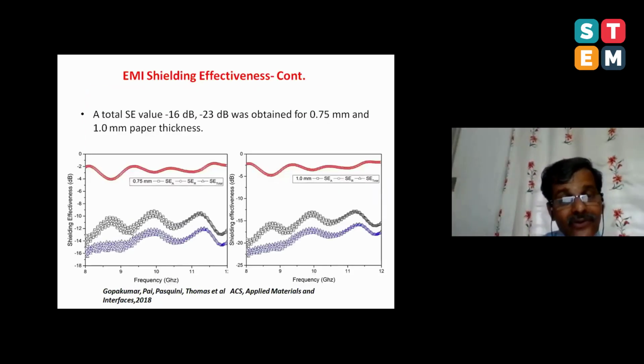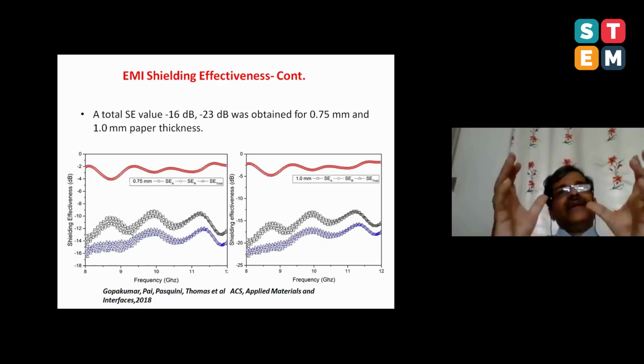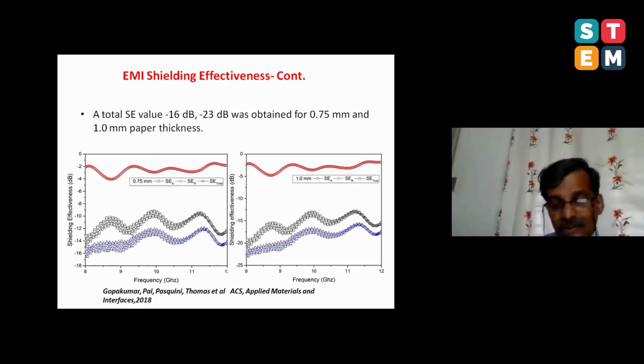What we have done, we have utilized this material for EMI shielding application, electromagnetic interference shielding application. There are a lot of requirements for EMI shielding. And look at what sort of shielding we got. We got something like 24 or 25 dB at a thickness of 1 mm. At a thickness of 0.75 mm, the paper gave 16 dB. So we made conductive, flexible, lightweight EMI shielders using nanocellulose extracted from waste.